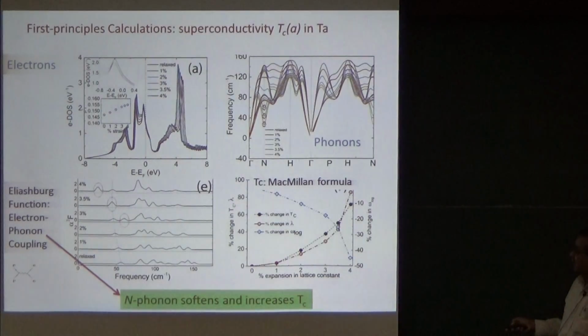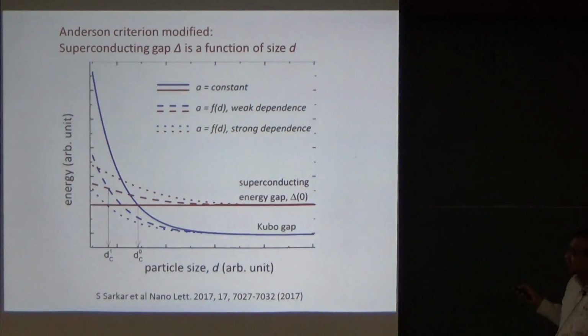TC. And as a result, the Anderson criterion gets slightly modified, in the sense that because the lattice constant changes with particle size, this would have been the standard Anderson criterion given by the solid line, and this would be the critical length below which superconductivity shouldn't exist.